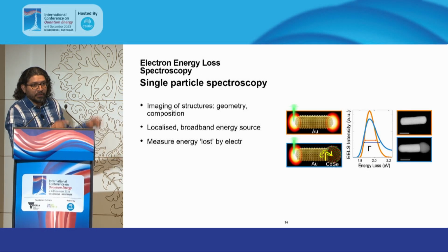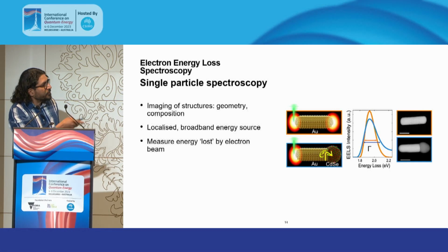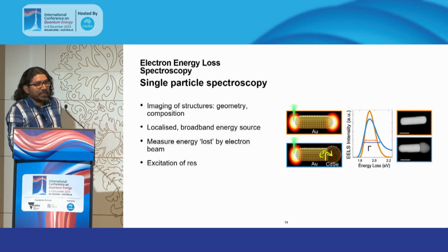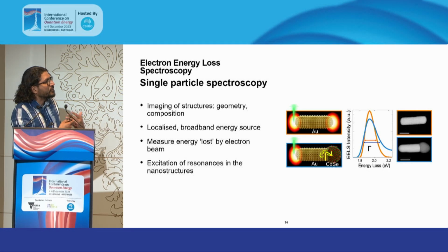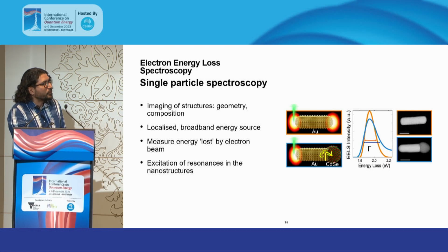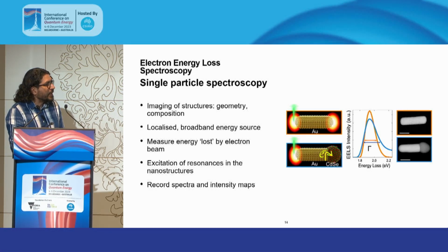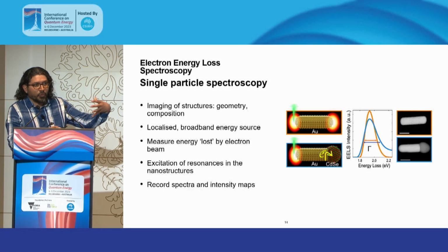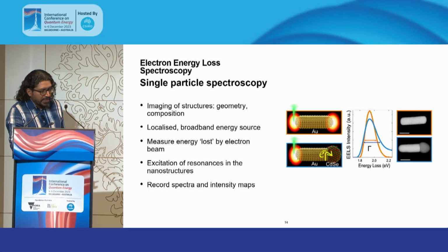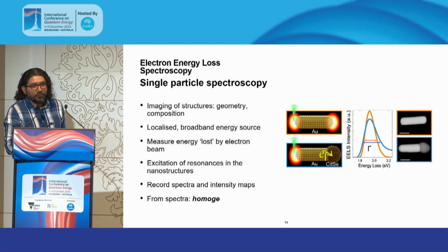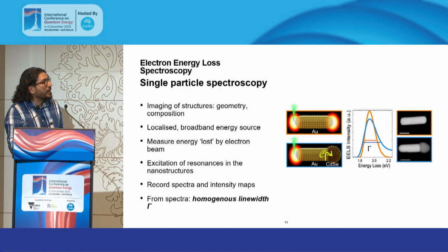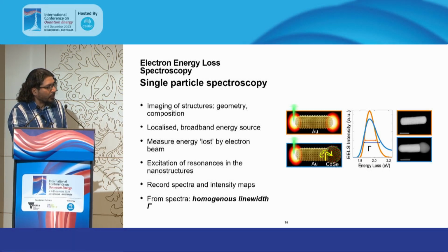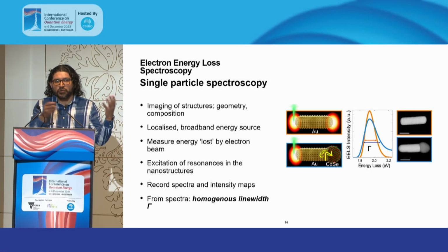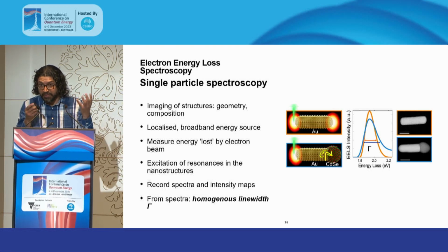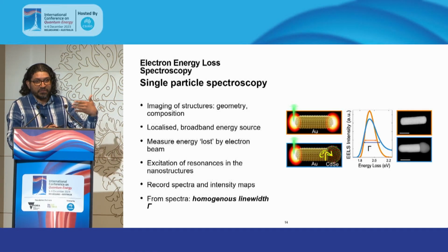So we can measure the energy lost by the electron beam as it travels through the specimen. And this energy lost is actually not lost. It's transformed into the plasmon resonances in the nanostructures. From this experiment, we can record intensity maps, as in where is the energy lost more predominantly across the structure. And we can also get spectra. From the spectra, the line width is the key parameter here, as this is the homogeneous line width, which is related to how the coherent oscillations of electrons, the plasmons, are losing energy via these dissipative processes.